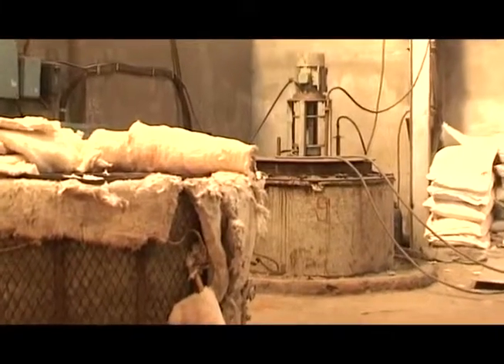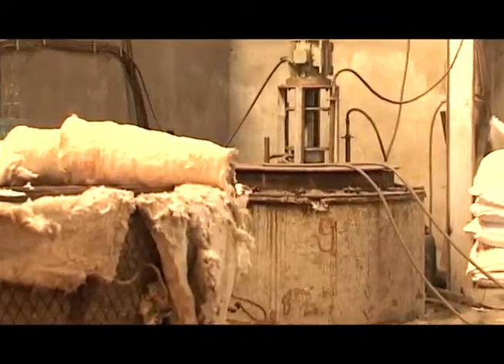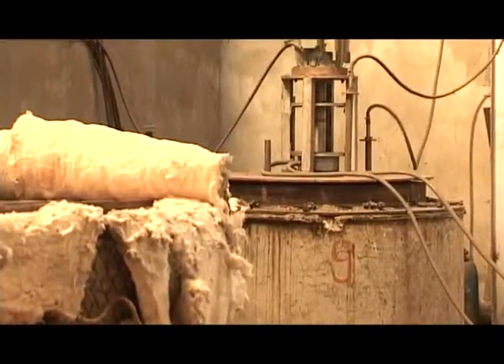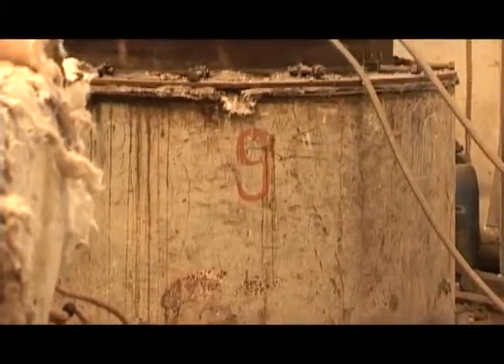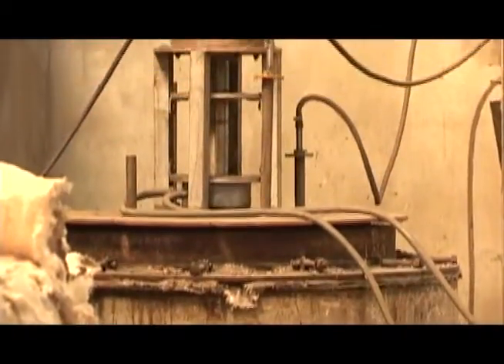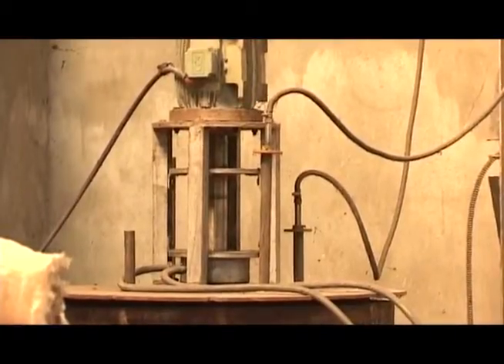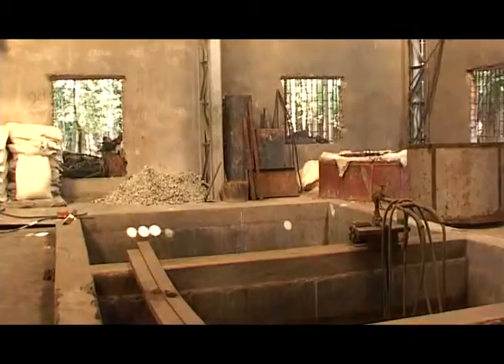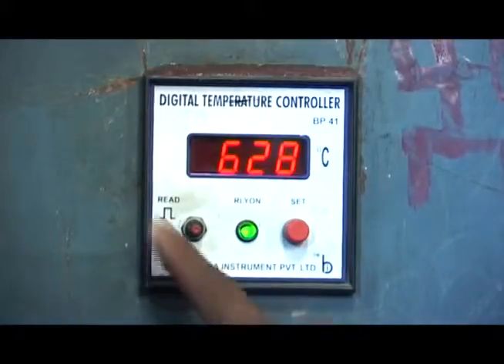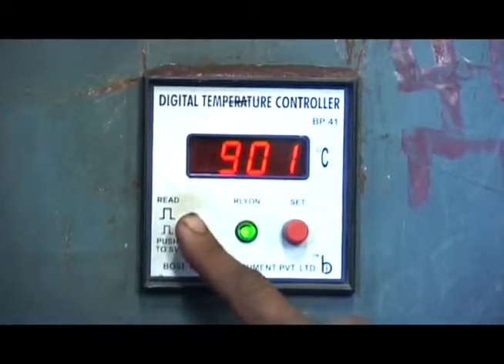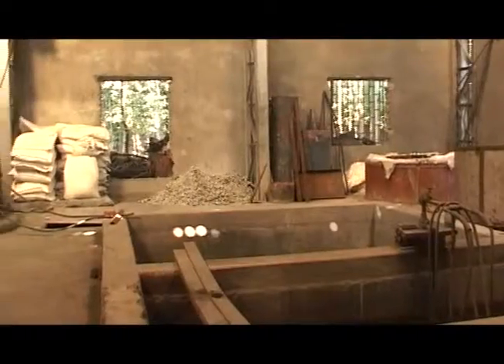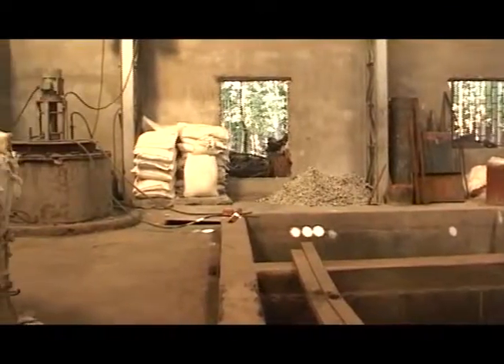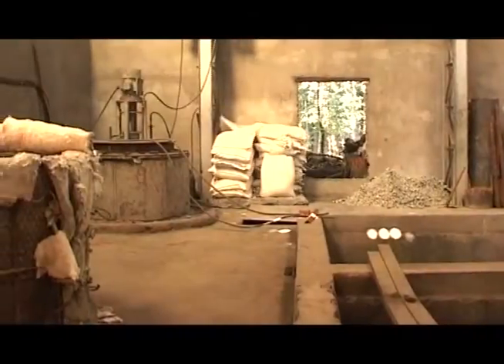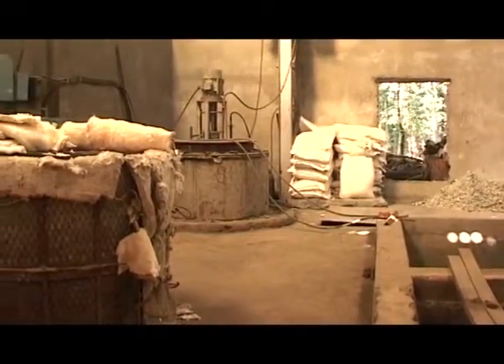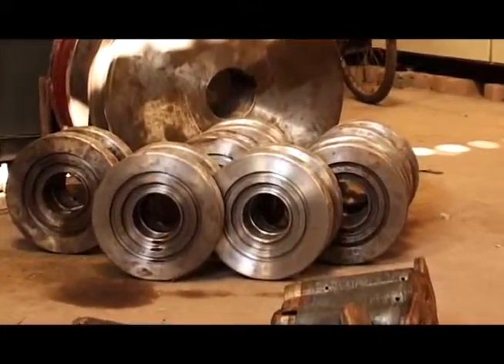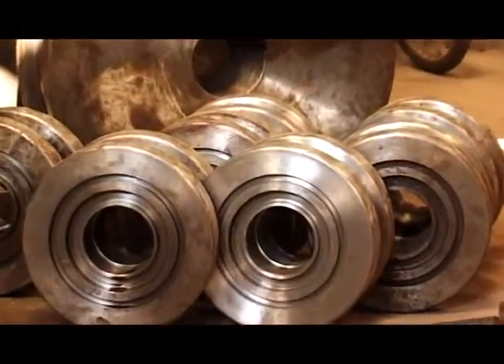Gas carburizing: optimum combination of high wear resistance and surface hardness with a tough core. Control of carbon potential in the process ensures proper case microstructure free from the carbide network. Case or core refining treatment achieves a fine-grained structure throughout the mass. Improved endurance limit in fatigue. Case depth 0.5 to 3 mm, different ranges, using conventional carburizing fluid. 0.1 to 0.5 mm, different ranges, using special carbonitriding fluid.